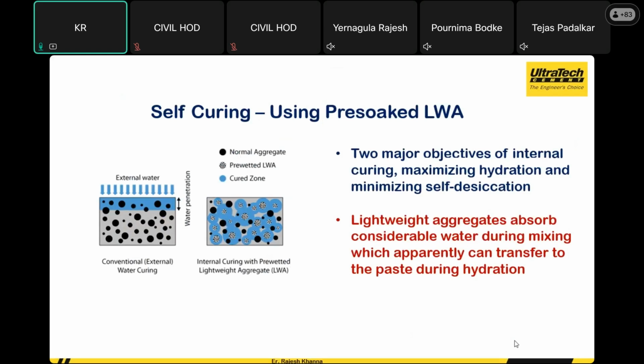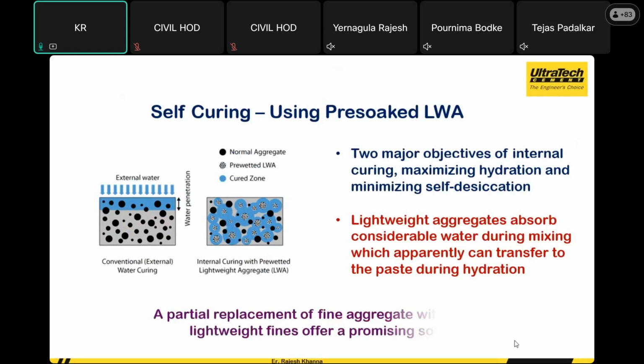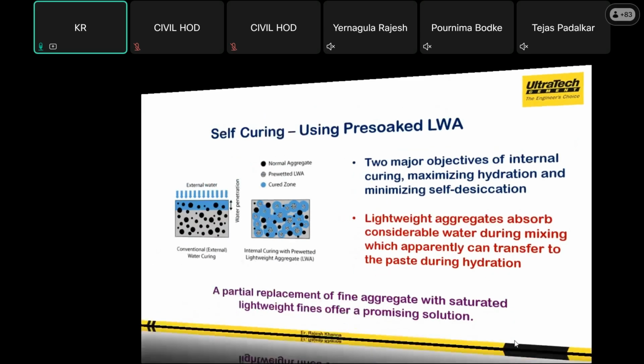Now we are doing it as an external application on concrete surfaces. Now a lot of research is happening where you can add pre-soaked lightweight aggregates, or there is an additive that is added at the time of batching, so that you just lay the concrete and leave it. It takes over the entire activity of curing that is required. There will be a slight drop of strength, but this is helping us save some of the water demand we have in construction, where water is much more required for curing. So this will be a partial replacement of the curing practices that we see.